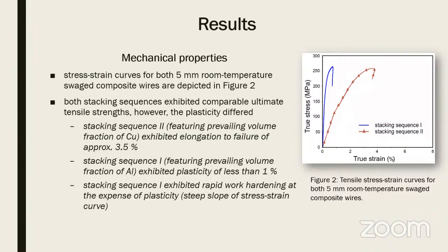We can explain this phenomenon by the hardening, which occurs primarily in aluminum, and because stacking sequence 1 consisted of aluminum sheet, this means the volume fraction of aluminum was higher in this stacking sequence, so the tensile behavior was mainly influenced by this hardening of this aluminum sheet. By this reason, the plasticity was so low for this composite or for this stacking sequence.